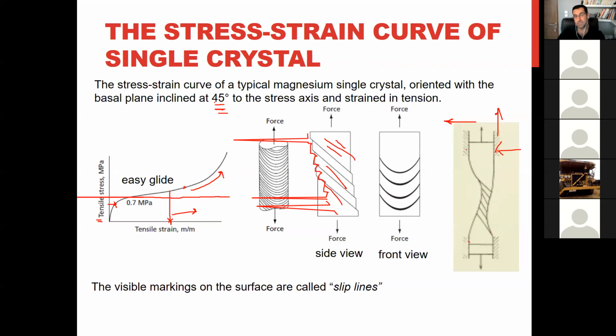And as we saw in previous slides, if we change this angle, you need higher tensile stress to reach that critical shear stress that you need for the slip. And this is happening here, it becomes like this, so this angle is no more 45, so the material starts to harden, the curve starts to increase and the slope will change. That is because of the way we are doing the test. If you have a machine where you can adjust the position of these fixtures, maybe you can continue deforming the material without doing this, okay?